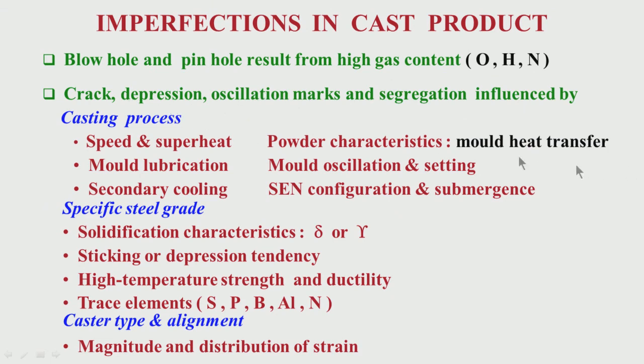Then there may be crack formation — this is very important. When solidification is taking place, the shell might develop some cracks. The shell has certain properties; it is at high temperature and slowly coming down to low temperature. At high temperature, what is the strength and toughness of the solid shell — whether it is delta or gamma or delta-gamma — they have different properties. Whether the shell can withstand ferrostatic pressure from inside liquid, and pressures during bending and straightening, will decide whether there will be crack formation.